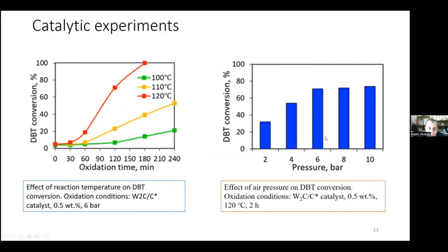We have also studied the effect of air pressure on DBT conversion. Note that at the minimum pressure of 2 bar, the oxidant to sulfur ratio is 17 to 1, which is enough for oxidation of the substrate. DBT conversion increases with increasing the pressure from 2 to 6 bar, which is associated with the increase in the solubility of oxygen in hydrocarbon fractions.